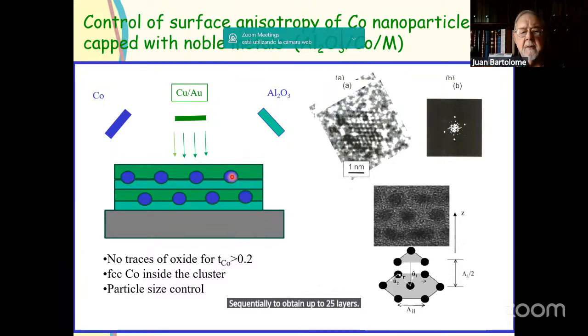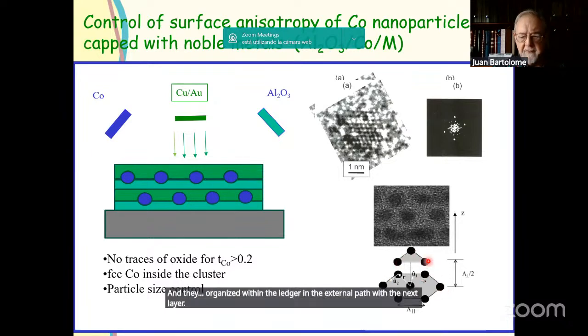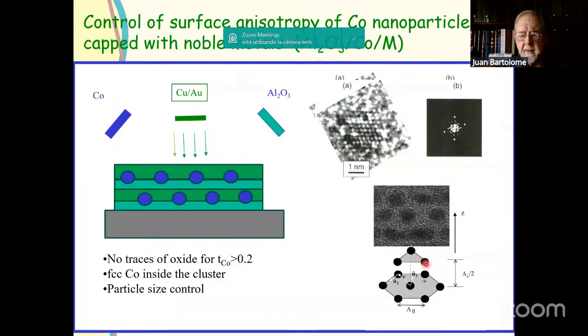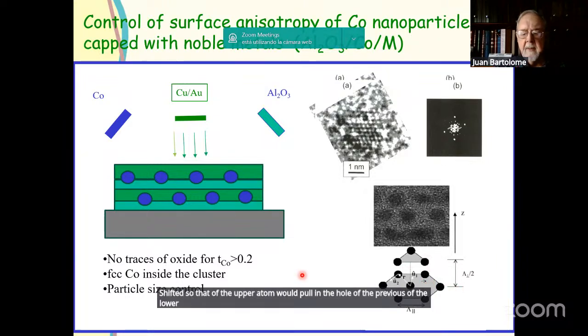Each of these cobalt particles crystallizes in the FCC structure, as you can see here from electron microscopy. And they organize within the layer in a hexagonal pattern, with the next layer shifted so that the upper atom would fall in the hole of the lower sheet.